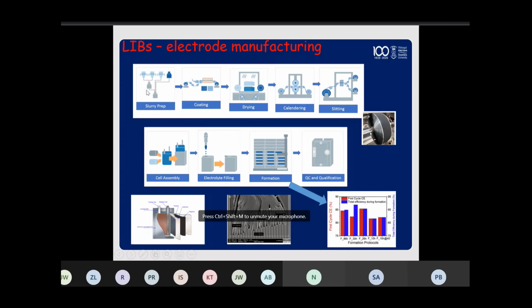This is when we mix the three components of the active materials: the active material, the binder, the plasticizer, and the electronic enhancer, the conduction enhancer. They're mixed with a solvent. In the old days, they used a very nasty NMP, which is now banned in Europe, and so now all manufacturers are turning to using water. These are mixed together to form an ink, of course.